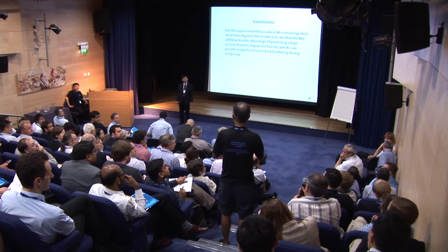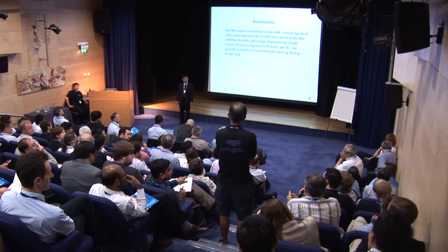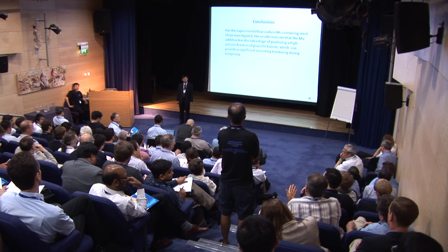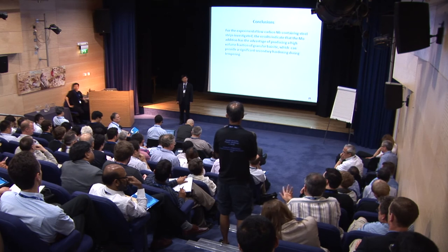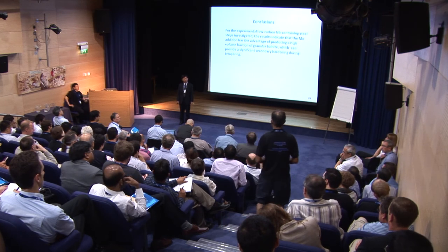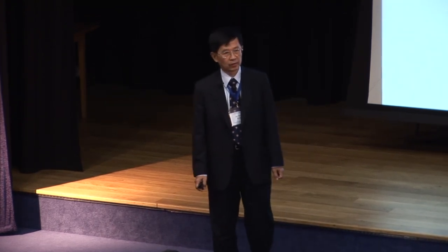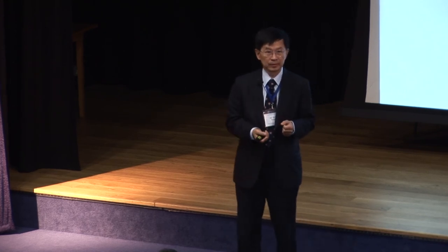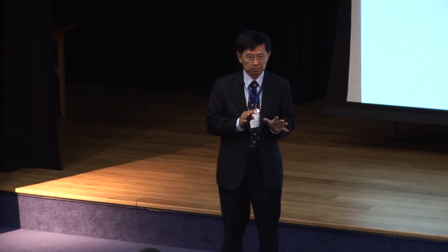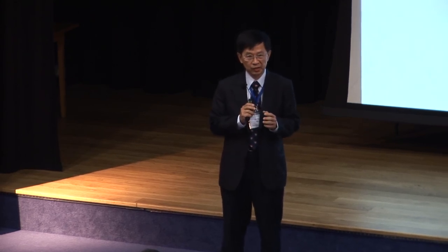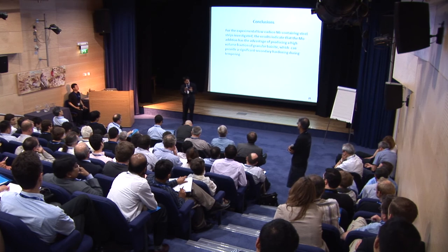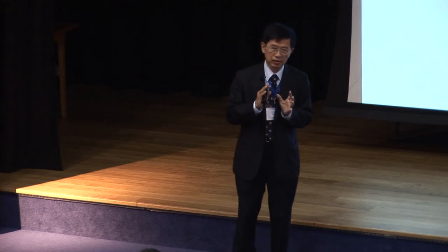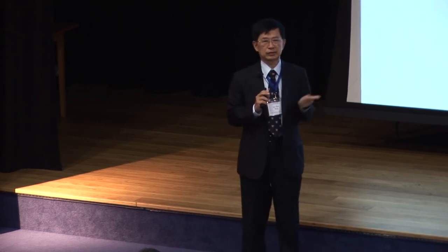So for example, the image quality that we use? Or different criteria. In a recent version of some software, you could use even a kernel map on the image quality. Do you have some experience with that? I think image quality is a good way, and also we should consider the dislocation density effect. There are several measures we can consider, and which one is the best is open. In fact, we have used image quality to distinguish the MA phases. It's quite easy because it becomes dark. For ferrite and bainite, we know the bainite has a high dislocation density, so some people will consider the image quality, but in fact we still can see it in our results.